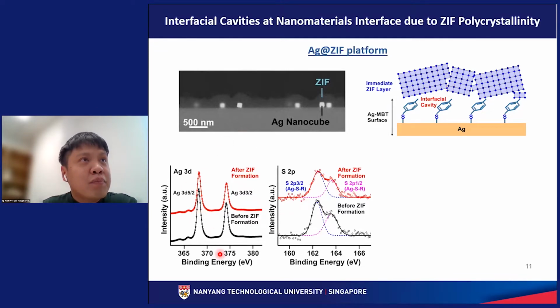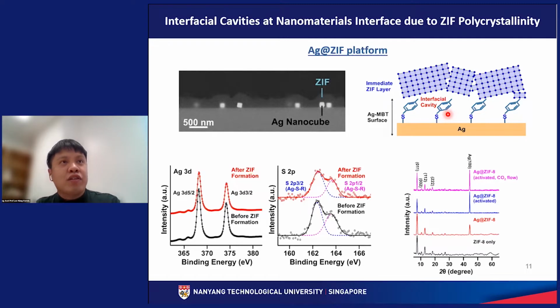So from this XPS characterization of Ag 3d and sulfur 2p, we can see that there is no interaction between ZIF and silver. Okay, so this means that the MOF layer or the ZIF layer is not directly in contact with the silver. So we expect interfacial cavity to be present. So again, the presence of ZIF layer over our silver nanocube is affirmed using X-ray diffraction.